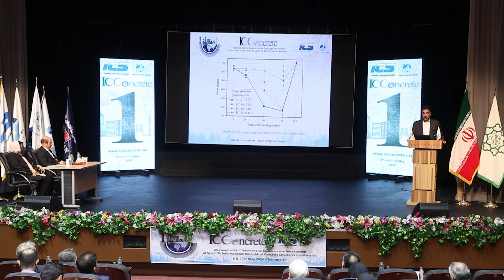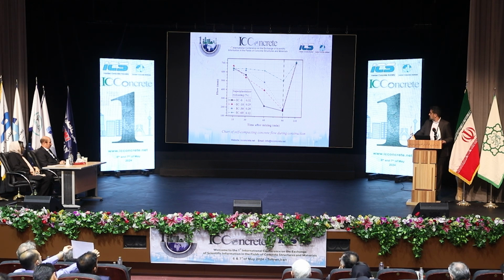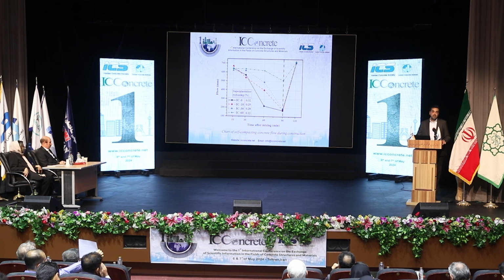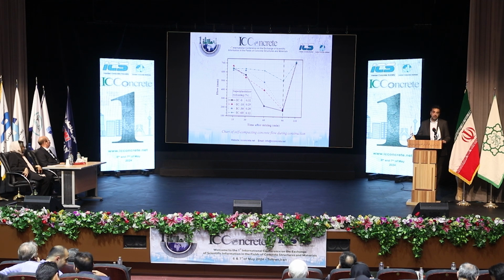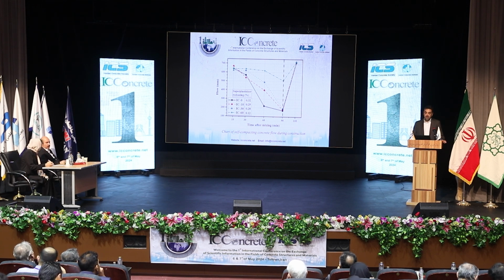In our research, we kept the initial flow of self-compacting concrete about 650 millimeters for all the mixtures. As you can see, the mixture with the highest level of crushed ice replacement, that is the IC60 mixture, where 60% of the concrete water mixture was replaced by ice, had the best slump retention after 90 minutes. With increasing the amount of crushed ice, the slump loss was lower.